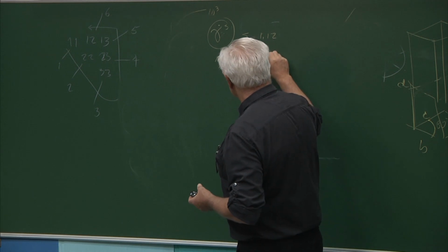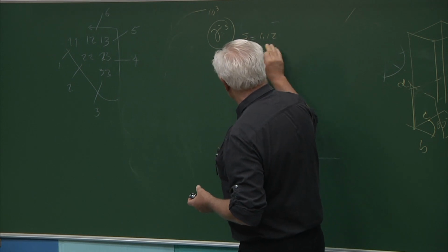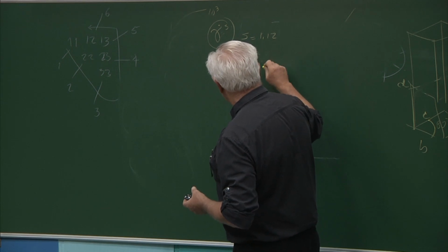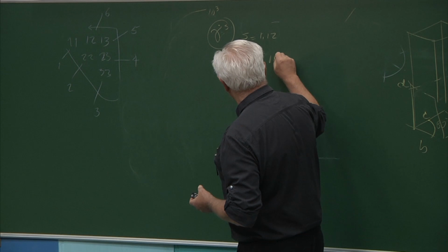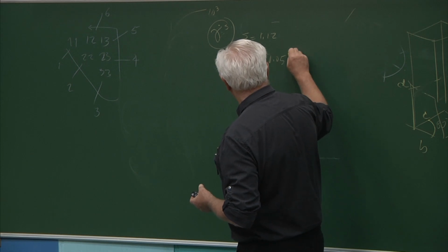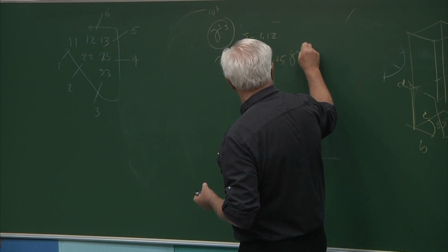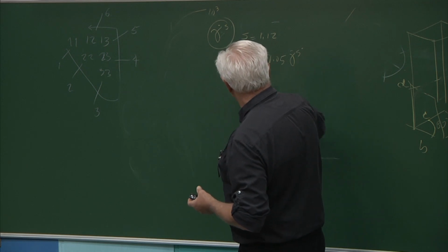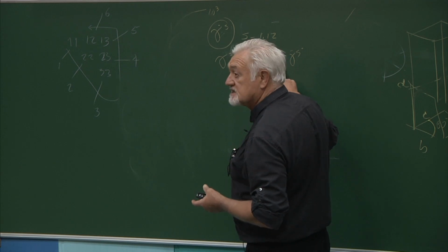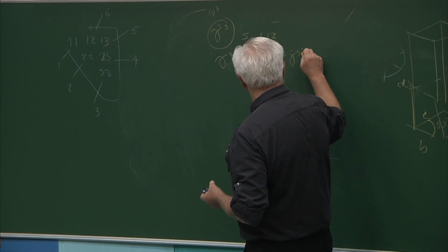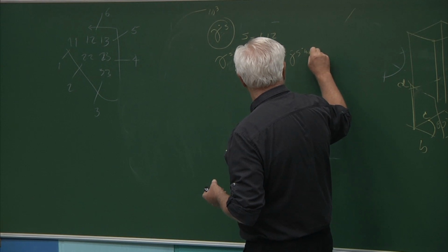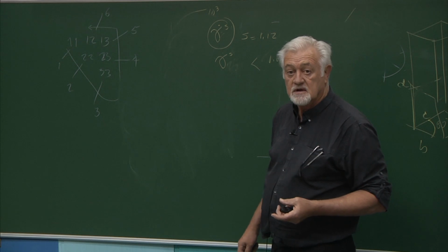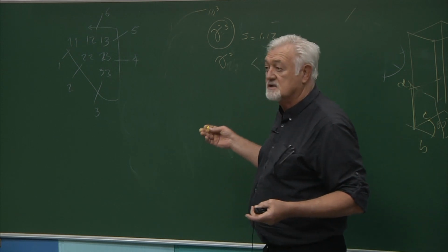And then any system gamma dot^s that is lower than 5% of the maximum gamma dot^s, you say that that system is not going to be counted as active. So that is how that is defined.